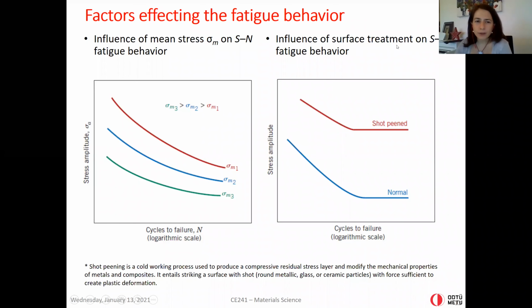So let's talk about two main factors that affect the fatigue behavior. The first one is mean stress. As you increase the mean stress, actually you make your material fail more easily. Here you see three curves on the left. The green one is the highest and the red one is the lowest mean stress. As you increase the mean stress, you increase the probability of failure. So number of cycles decreases.